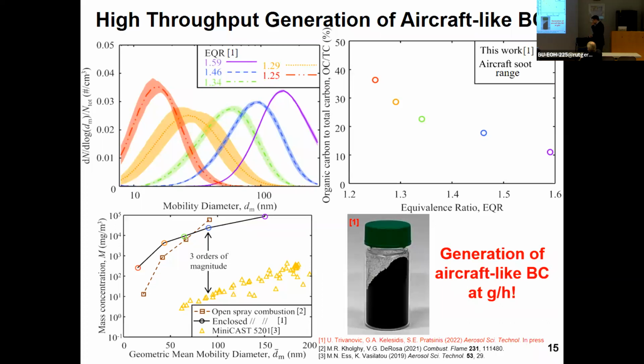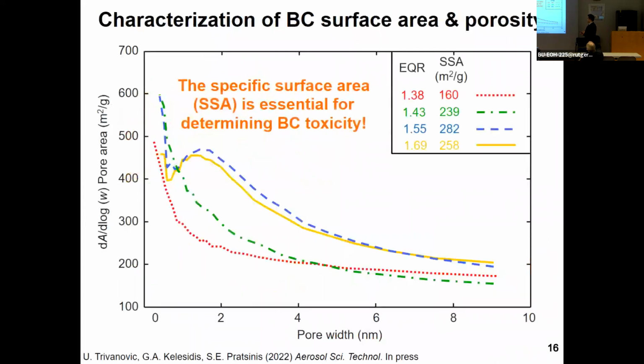So the idea here is that we can use this reactor to generate black carbon nanoparticles that are similar not only to aircraft engines, but different kinds of sources of black carbon emissions. And first of all, we can characterize physical properties that are relevant for their toxicity. So this is actually what we did over here in our recent paper. We managed to get the specific surface area as well as the porosity of these nanoparticles.